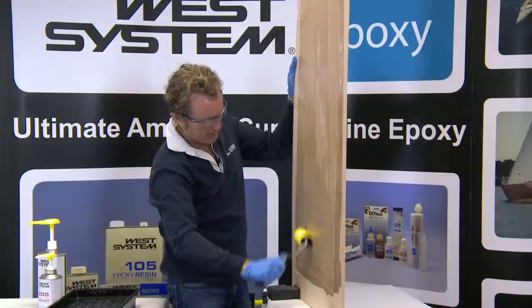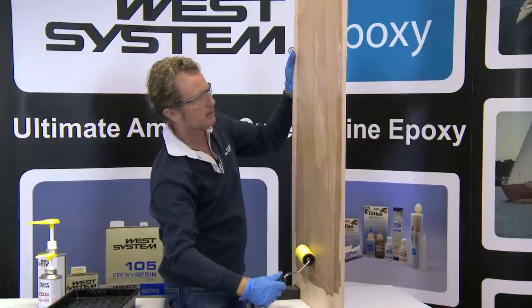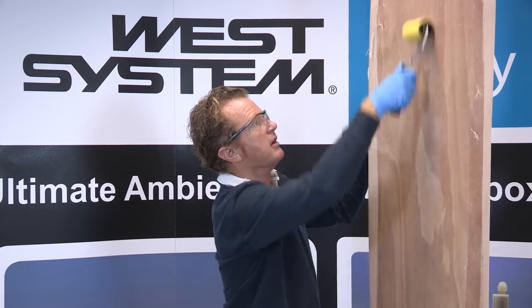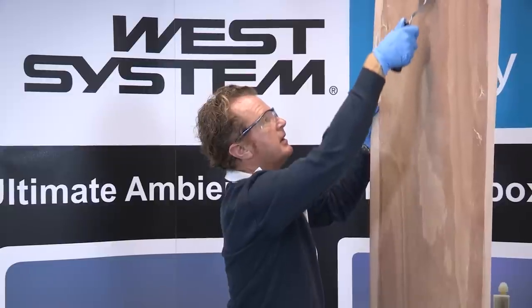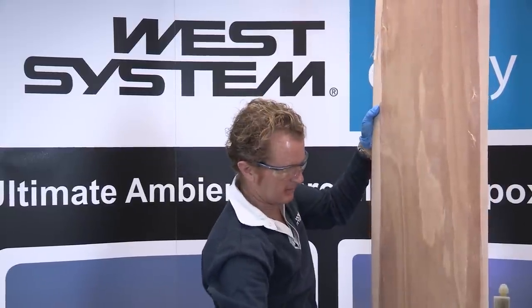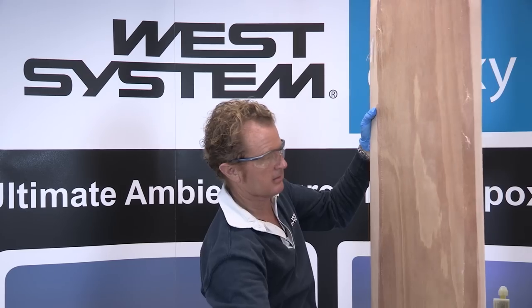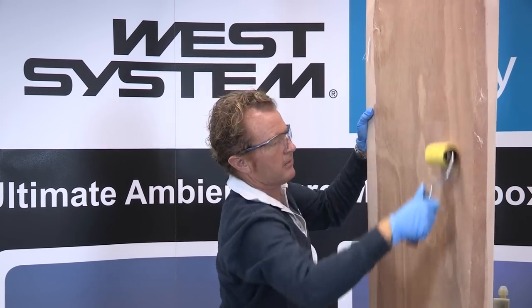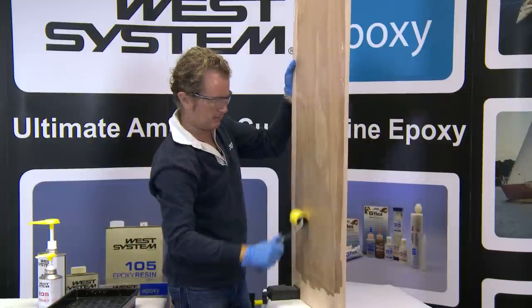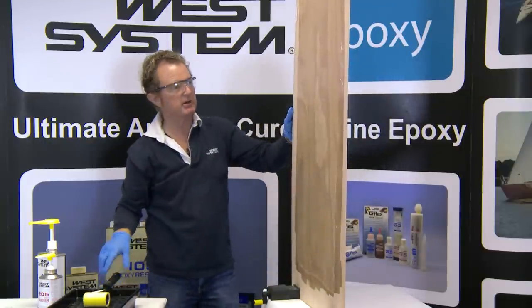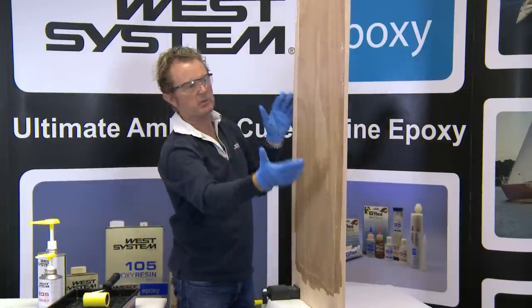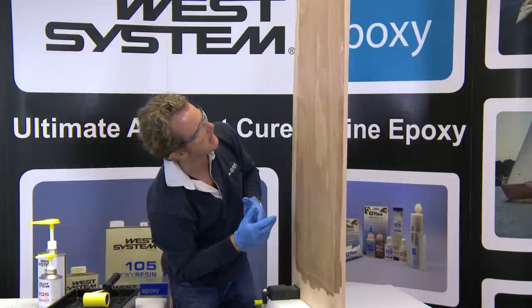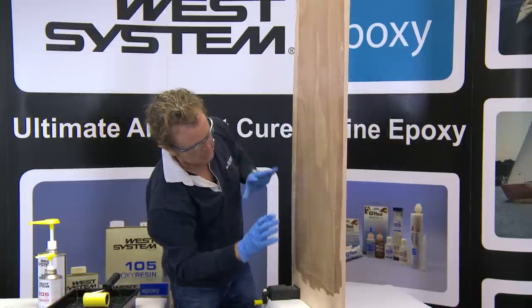And now I've got no air bubbles under the glass cloth. The action of the roller is driving those out. And you can see now I've got the glass cloth thoroughly wet out and I've consolidated it and I've got no air bubbles or dry spots so that the glass is floating.